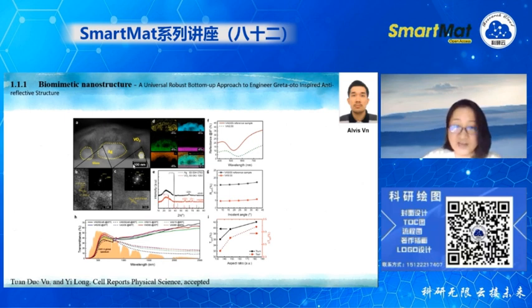On top, we have vanadium dioxide. The other thing is, because once you have graded structures, it becomes this anti-reflection. So it is angle independent. This is also very important, right? It's angle independent because if you have other size structures, they have a certain angle, so a certain angle has better anti-reflection, but some others do not.